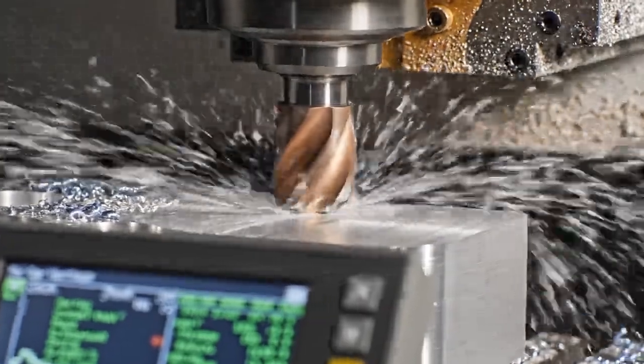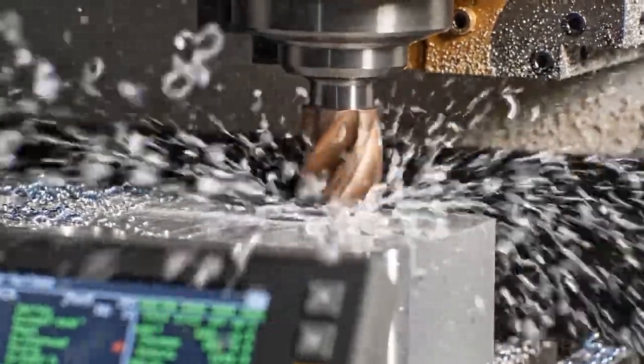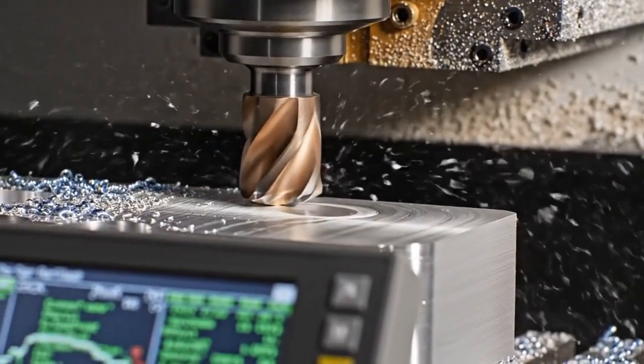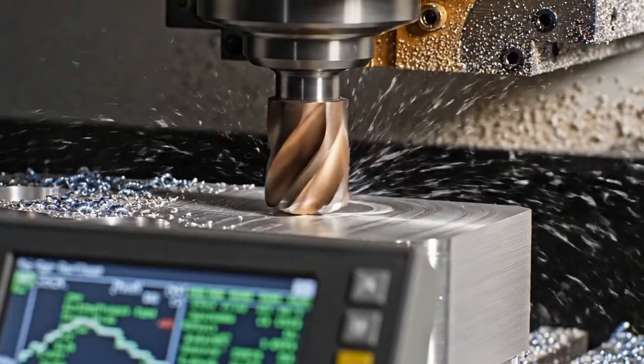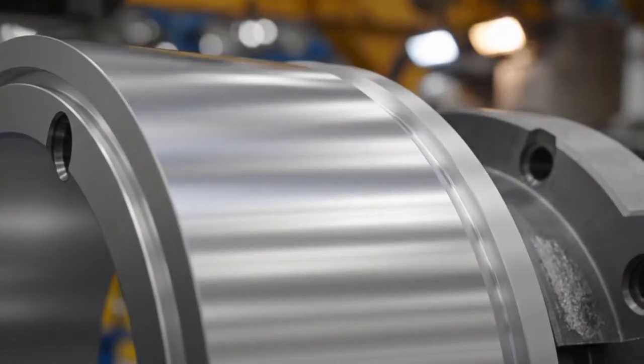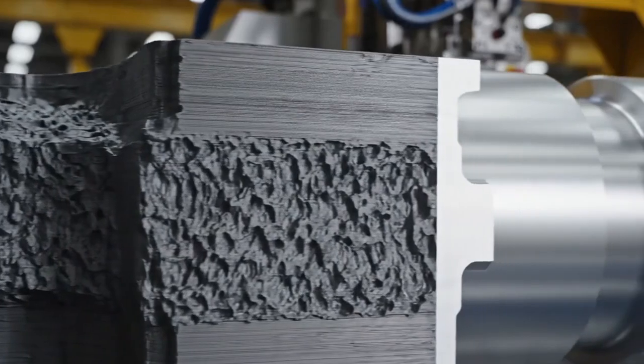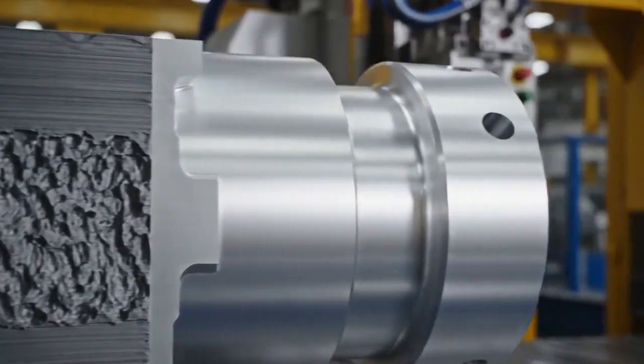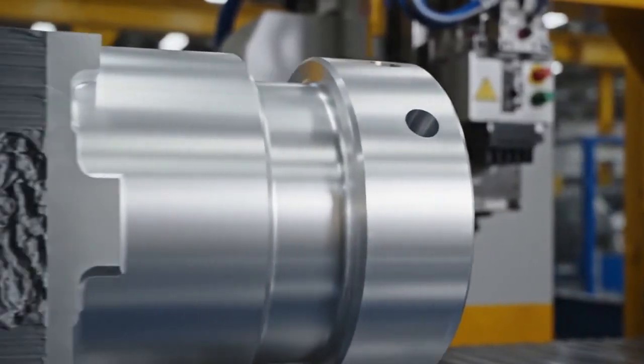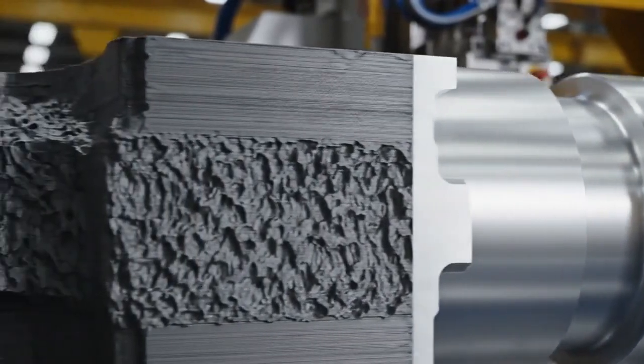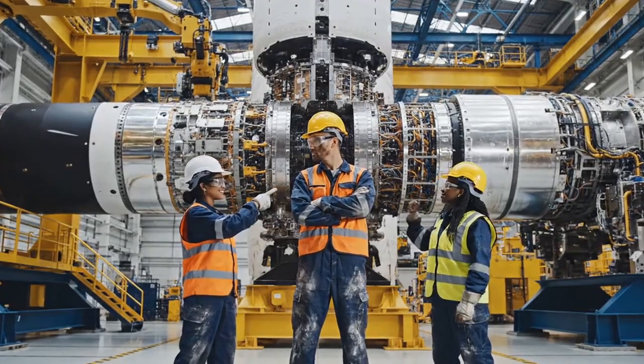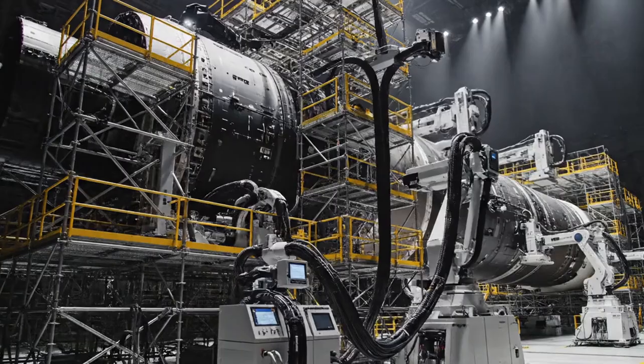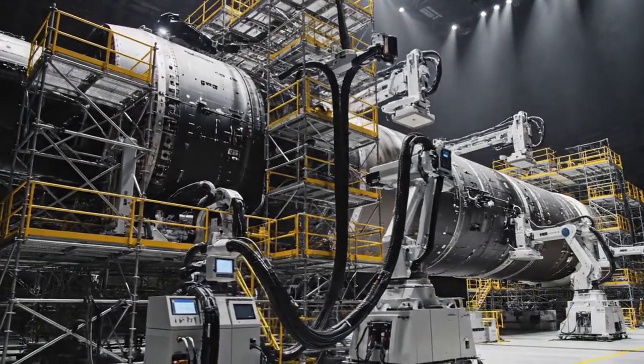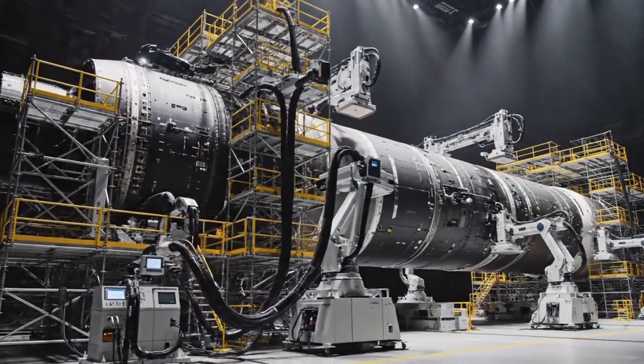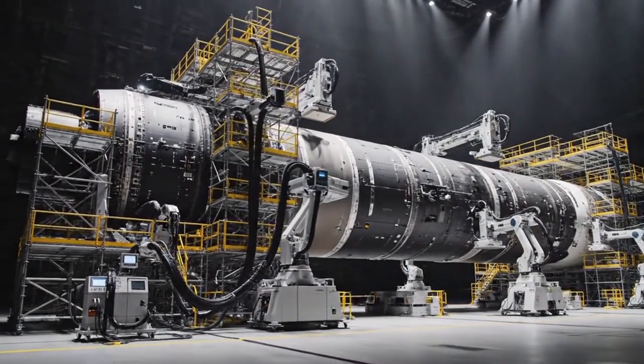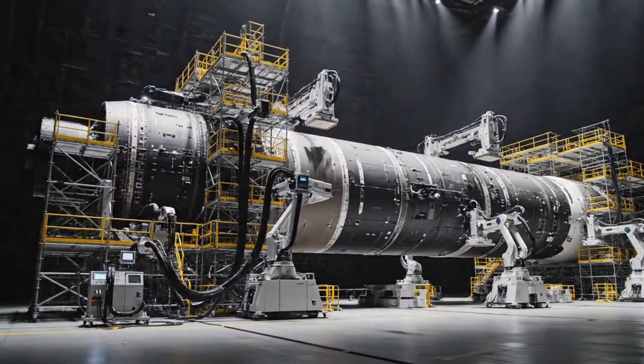Here, carbide cutting tools rotating at thousands of revolutions per minute shave away microscopic layers of the rough printed aluminum, achieving surface finishes measured in fractions of a micron. This hybrid manufacturing approach, additive for the primary mass, subtractive for the critical mating interfaces, represents the absolute apex of current industrial capabilities. Before the monolithic structure can be integrated with its propulsion systems, it must undergo a rigorous suite of non-destructive testing, or NDT.